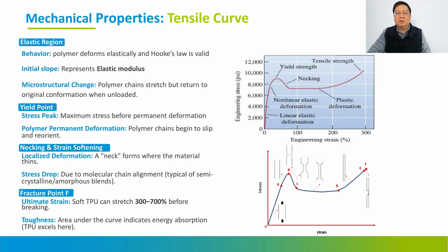And the negative slope means that the material becomes thinner, and the stress drops, which means this material has already been stretched too much. And the fracture point means if you really stretch the material too much, then it will break. Toughness is the energy absorption. I would say that with multilayer, if they combine with a very good, tougher polyurethane in the middle, they can absorb more energy, which means the crack resistance is much better than other materials.